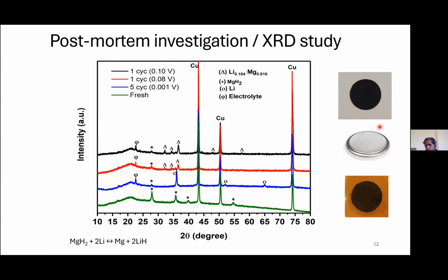We just break the batteries, whatever we assembled, and we take it out. We break the battery inside the controlled atmosphere, which is a glove box. And in our case, it is the anode. We take it out and laminate it thoroughly so that when you take it absolutely outside of the glove box, it will not oxidize. And then we do it. By the way, it is a Kapton film. It's an X-ray amorphous film, so it only gives you the characteristics of the sample. All right.